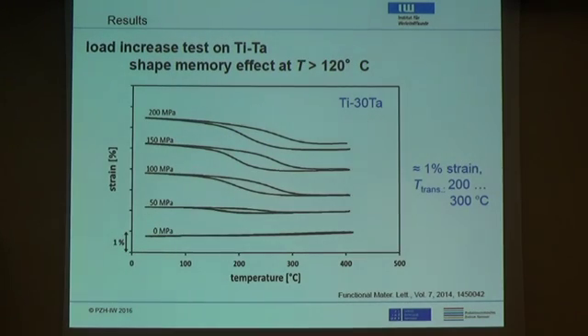So we started with so-called load increase tests. Here you see the strain on the material, and this is the temperature. We heat up the sample from room temperature to above 400 degrees C, and cool it back down. If you do not apply a stress, you don't see much, right? But if you do apply a stress, then certain martensite variants are favored, and suddenly you see a transformation strain. As you increase this stress, you get more and more strain, and in the end you get around 1 or 1.5% strain. And the good news is the temperature where this phenomenon happens is around 200 to 300 degrees C. So it looks like an interesting material.